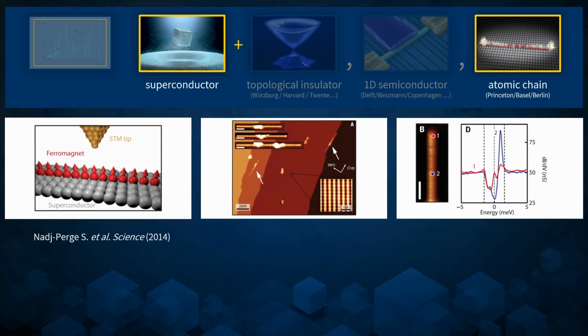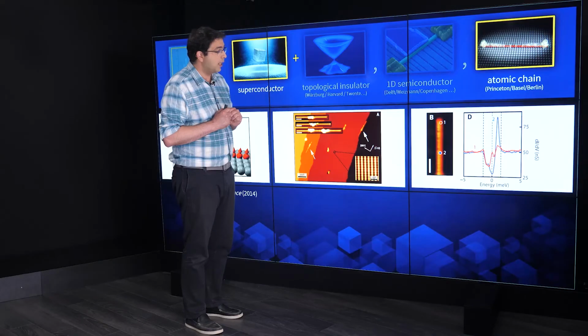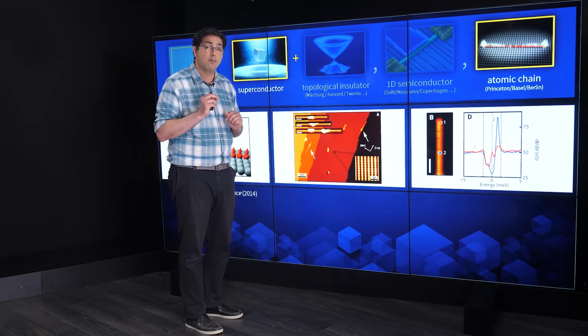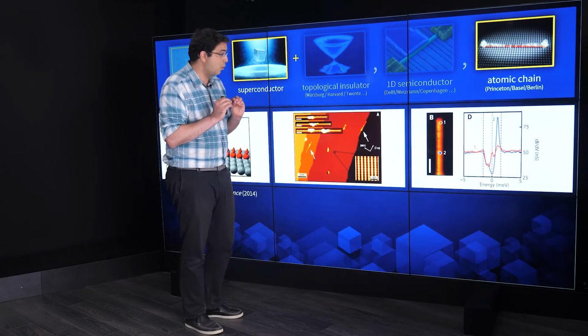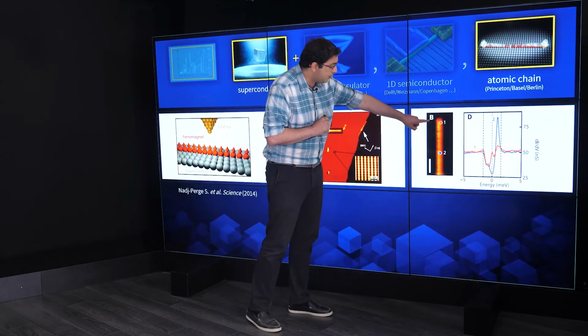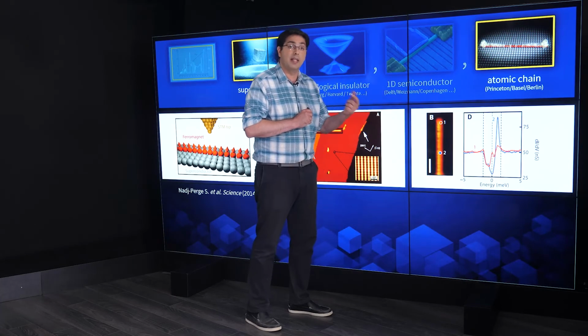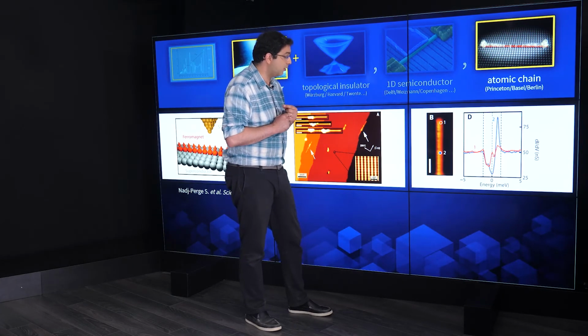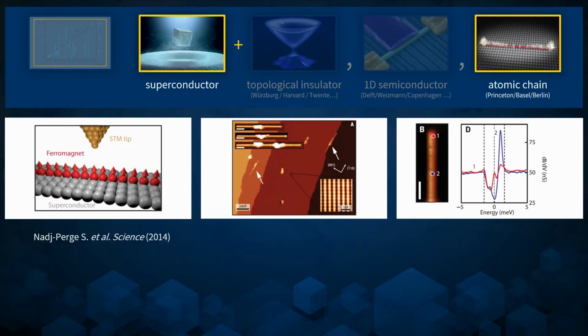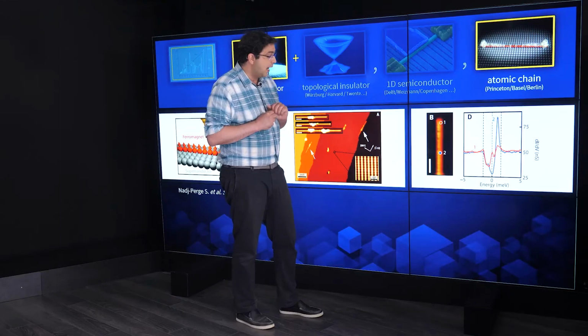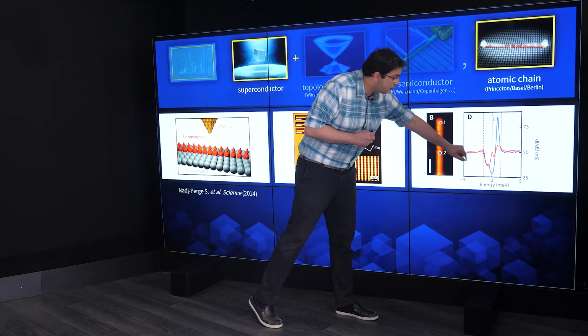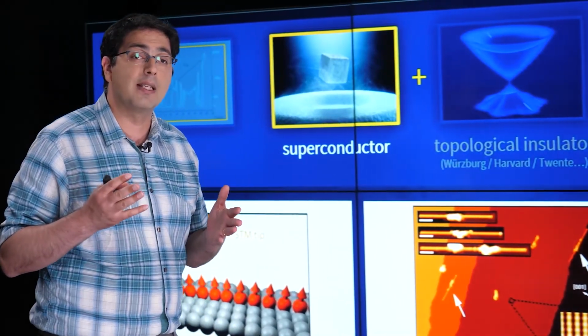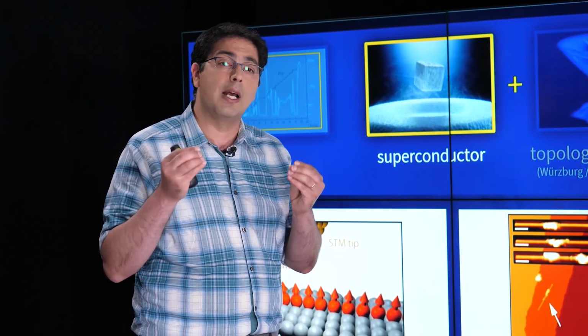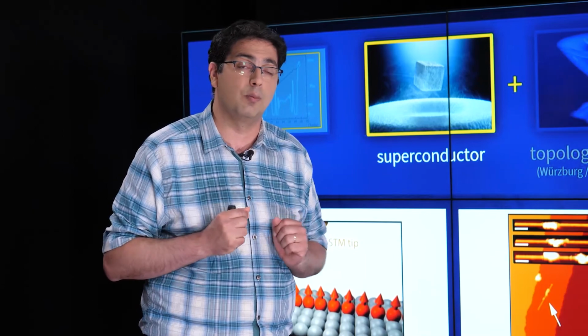Now, what you can see on the right side is the STM image itself. What they did here was a spectroscopy measurement as a function of x and y. You can see in red the spectroscopy measurement at point 1, at the edge of this line of atoms. And in blue, you can see the bulk. In the red, you can see this zero bias peak, which is telling us that there is a localized state at the end of the wire. And in blue, we can see these symmetric peaks, which are basically the Shiba states. The Shiba states are the states which are formed when you have a localized magnetic impurity which is proximitized by the superconductor.